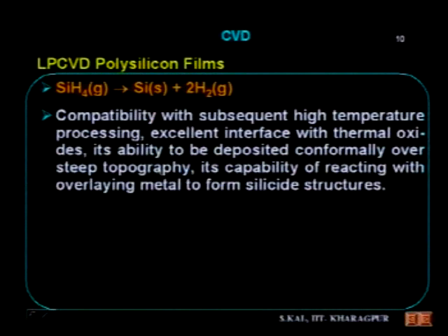Compatibility with subsequent high temperature processing, these are the characteristics of LPCVD polysilicon films. You can achieve an excellent interface with thermal oxide of silicon. You can grow polysilicon film on silicon dioxide. Sometimes we require those films. Excellent interface with thermal oxides.